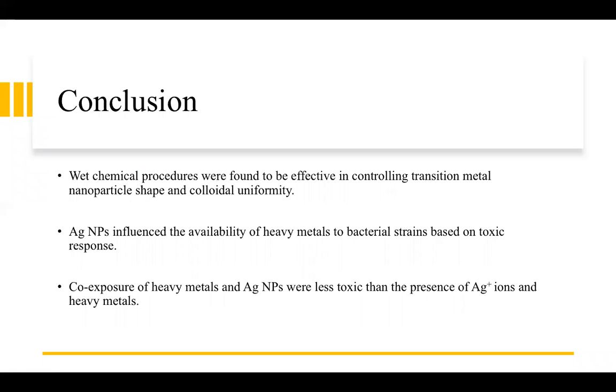We also see that silver nanoparticles influence the availability of heavy metals to bacterial strains. So thinking about the hypothesis that silver nanoparticles are going to change based on the environment that they're in, what happened, from our data, is that the silver nanoparticles actually inhibit, or it looks like they inhibit, the uptake of some of those heavy metals by the bacterial strain and actually have their antimicrobial properties being seen. And our last conclusion from this data was that the co-exposure of heavy metals and silver nanoparticles was less toxic than the presence of silver ions and heavy metals alone.